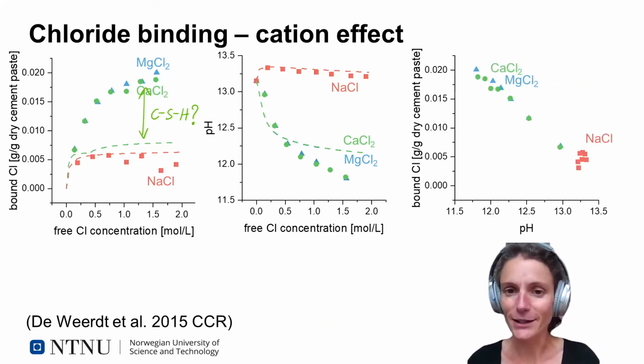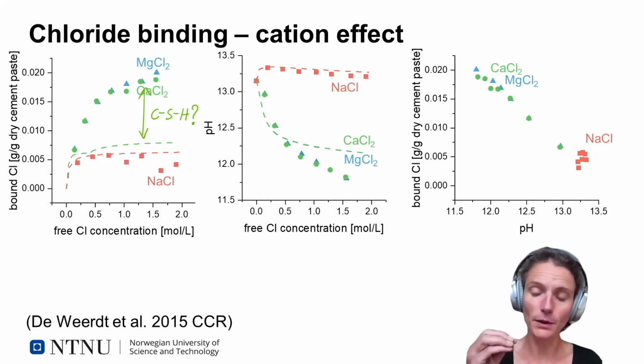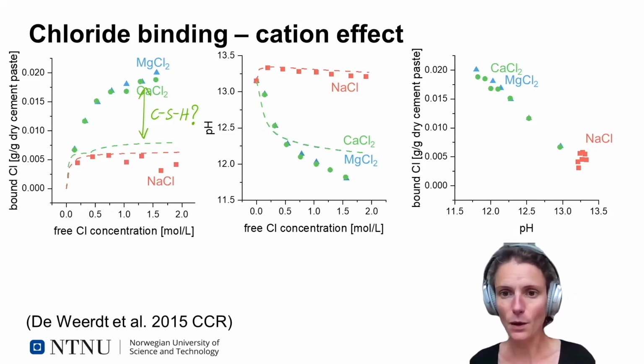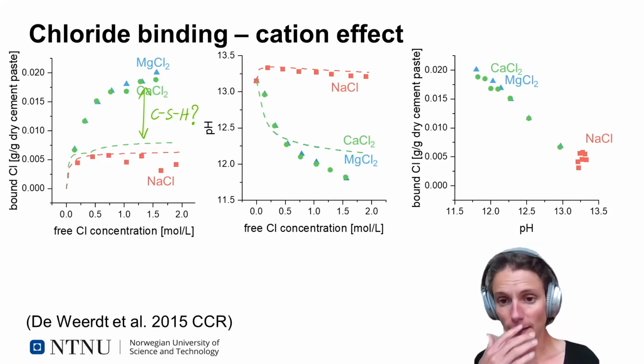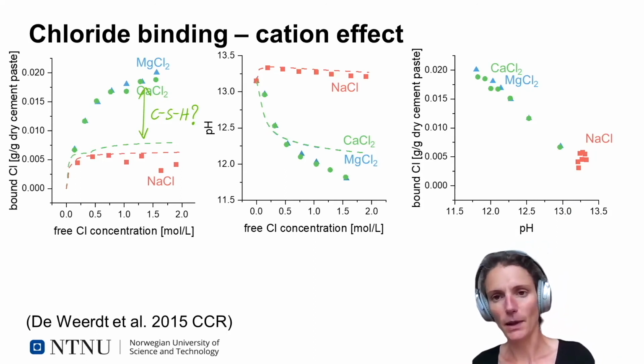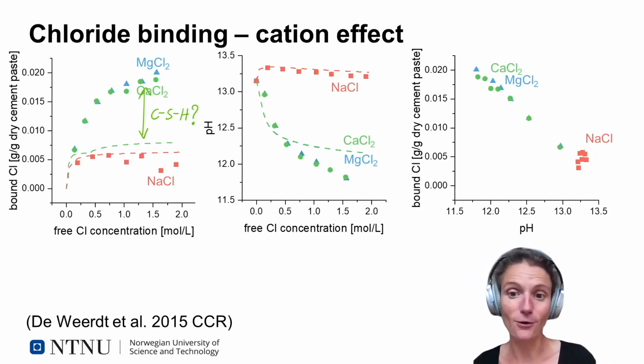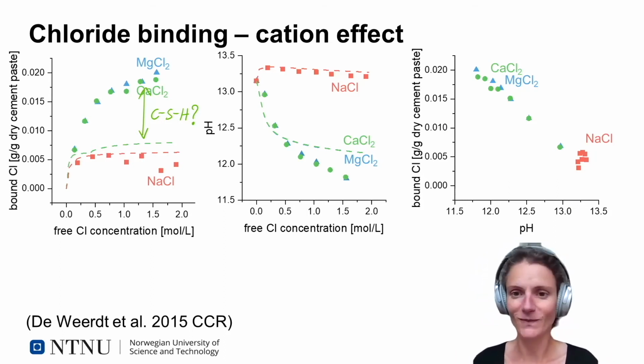Another thing we saw in the study is when we plotted the amount of bound chlorides as a function of the pH, we got a nearly linear relationship. So this, of course, is only a limited amount of samples and it's only one cement composition, but we could see that the amount of bound chlorides seems to increase when the pH decreased. And that triggered the idea for us for the next study.